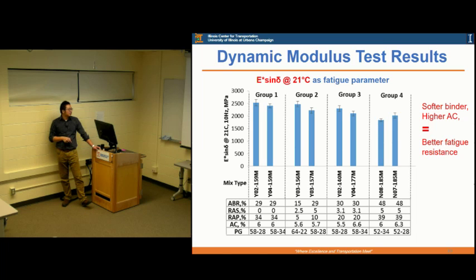Basically, if we put the mix design information here, we found that if we get a softer binder, for example, look at these two in group 1, this one has a soft binder because the low PG is -34. You have a soft binder, so you end up with a lower E star times phase angle, which means you have a better fatigue resistance.